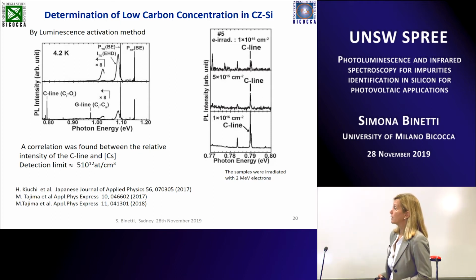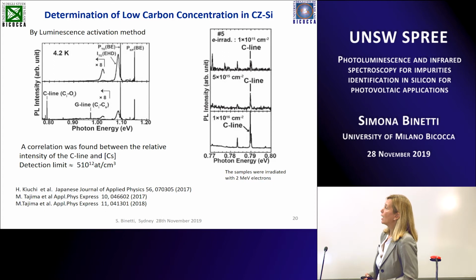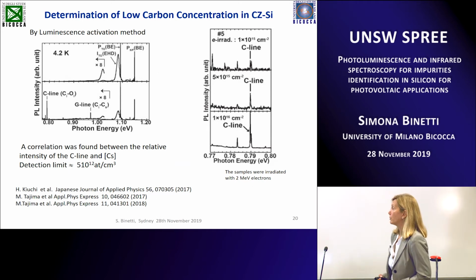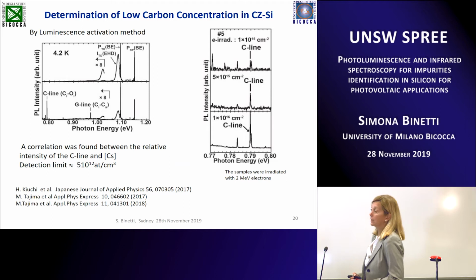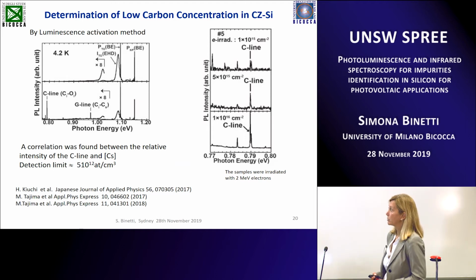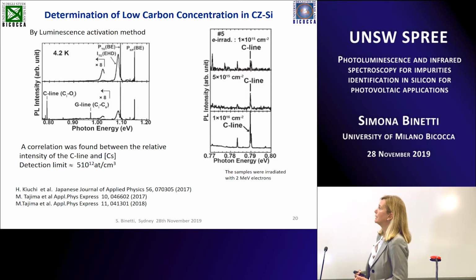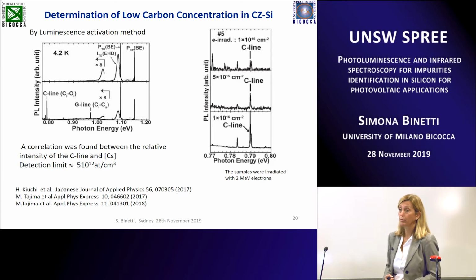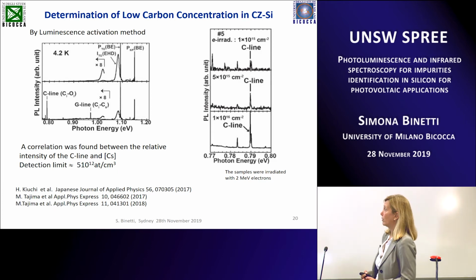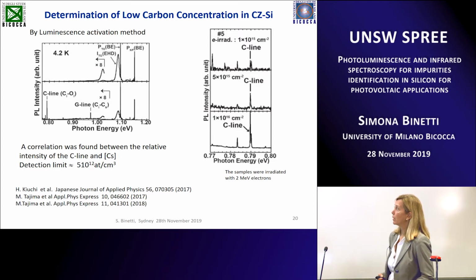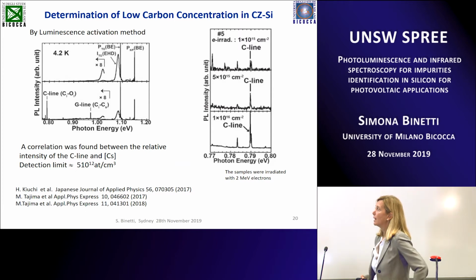And so by photoluminescence a new method has been developed that has been calibrated in order to have a correlation between the C line and the carbon concentration. The drawback of this method is that the sample must be irradiated with 2 MeV electrons, so it's not a simple process, but in any case you can have a detection limit up to 5 x 10 to 12 atoms per cubic centimeter. And a correlation has been found between the relative intensity and the concentration of carbon.